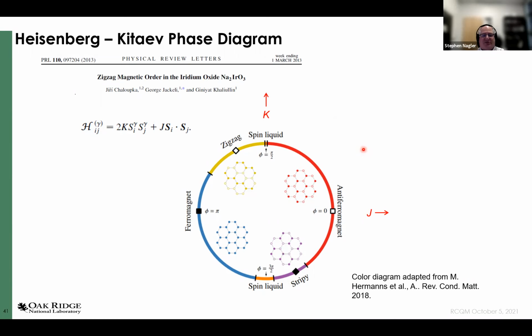But you'll notice that actually this Kitaev ground state, the quantum spin liquid, survives in both the antiferromagnetic and the ferromagnetic limit. Now, one of the reasons that this survives is effectively there's a topological protection. So just breaking the symmetry of this by adding in some extra interactions does not destroy those spin liquid ground states necessarily, right? It depends on the ratio of the interactions.